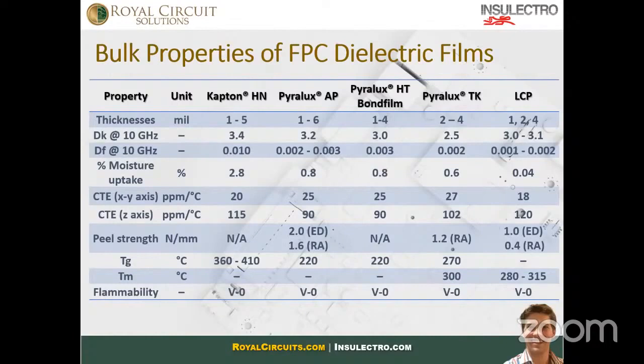When we look at something like Pyralux HT, that's our high temperature thermoplastic film. So if you need to do something that's under hood or you're down well in some kind of oil rig, we have different adhesives that'll work in different temperature environments. And Pyralux TK is actually a Teflon clad polyimide. So we can do all kinds of things with polyimide films that we couldn't necessarily do with rigid material and make them flexible at the same time.